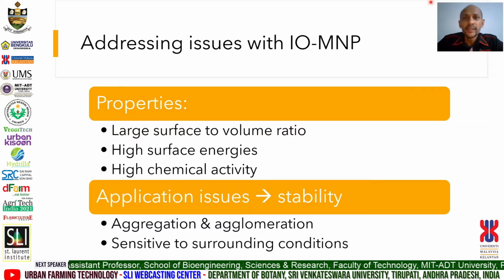So, wouldn't it be advantageous to use iron oxide magnetic nanoparticles where one can recover the iron oxide with an external magnetic field? However, iron oxide magnetic nanoparticles have large surface-to-volume ratio and possess high surface energies. Coupled with high chemical activity, they are easily oxidized in air, especially magnetite, generally resulting in loss of magnetism and dispersibility. Due to this, stability issues are of concern when it comes to application, especially in solution like in water treatment.